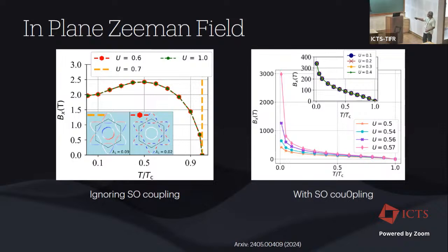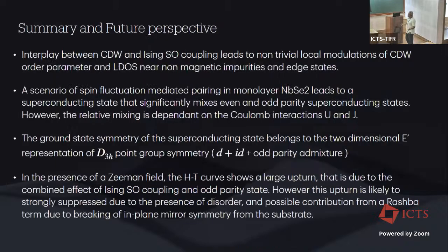But if you now include the effect of spin-orbit coupling, at low temperatures you get an extremely large upturn. For real systems, you can show that in the presence of disorder, which reduces the strength of spin-orbit coupling, that upturn can be significantly reduced. But this upturn is there and has been seen in many dichalcogenide superconductors. So with that, I think I'll just display the summary slide.